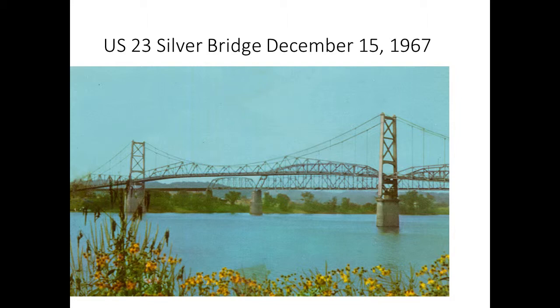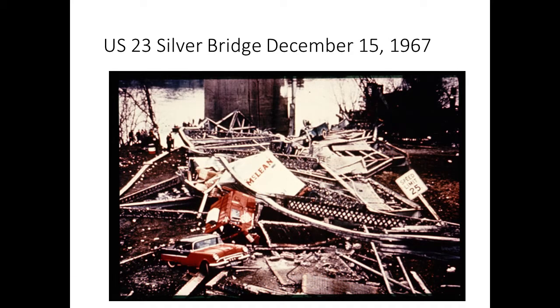But the bridge had several problematic features. The eyebar chains were fracture critical. They were made of a high-strength, low-toughness material. And then the towers were rocker towers, and if one of the chains failed, then the tower would become unstable and it could collapse. And unfortunately, that's what happened.